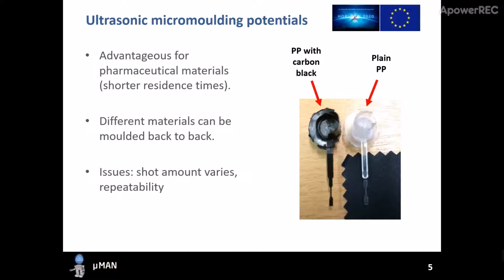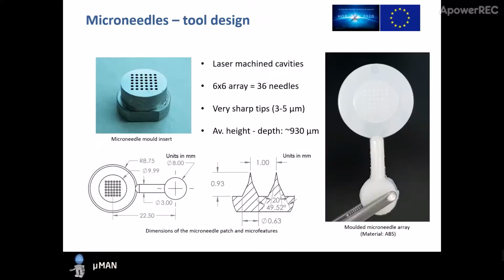Another advantage is that different materials can be molded back to back without any purging or contamination effect. One example we did was this polypropylene with carbon black on the left side here, and in the next shot we used the virgin material, and we had no contamination at all. So this could be another advantage for some applications. But there are some issues with this process as well, where the shot amount varies because of the shape of the pellets, and this sometimes causes some repeatability issues.